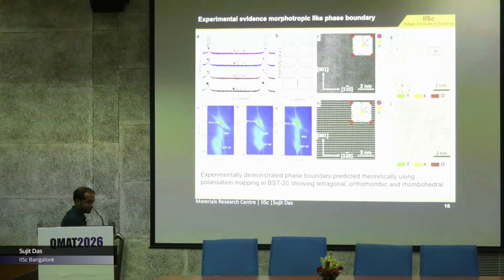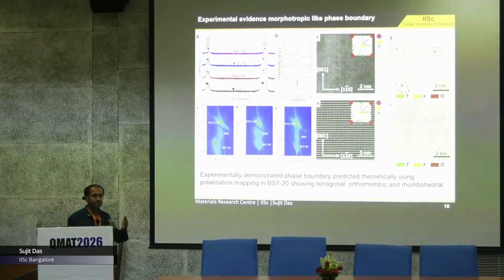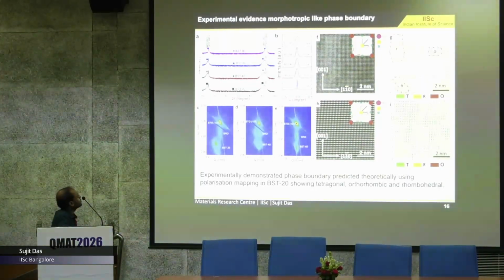The film peak is quite broad. Basically, the film peak is trying to split. This is also a signature that it has a mixture of different phases, and that is further confirmed when we did the cross-sectional transmission electron microscopy.